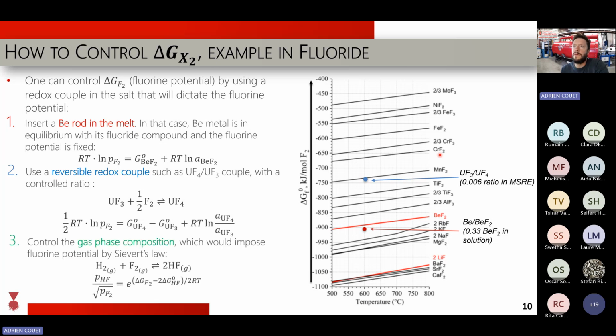And another way to do it, although it's not very much used in real applications, is to control the partial pressure of your gases in the overhead gas. If you do so, then you can control the partial pressure of fluorine in the gas in equilibrium with the partial pressure of fluorine in the salt. You will achieve, again, a redox condition. So if you control the HF/H2 ratio in your overhead gas, you decide where you want this point to be, and you can be more or less oxidizing. All right, so that's cool, but not very much used.